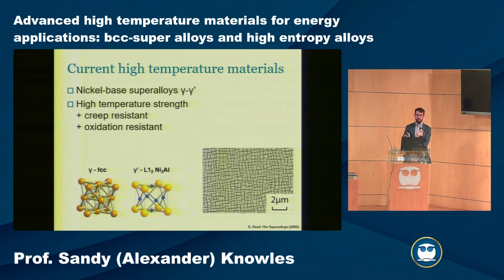So when we think of current high temperature materials, if we look at gamma prime in nickel-based superalloys, these are the state-of-the-art materials used in jet engines. They can be hugely expensive. You're happy to use elements like rhenium in them. Nickel itself is already pretty expensive. And in these, the fantastic thing about them is you get the high temperature strength, but also the creep resistance and oxidation resistance. And this critically comes down to the phase metallurgy within the material.